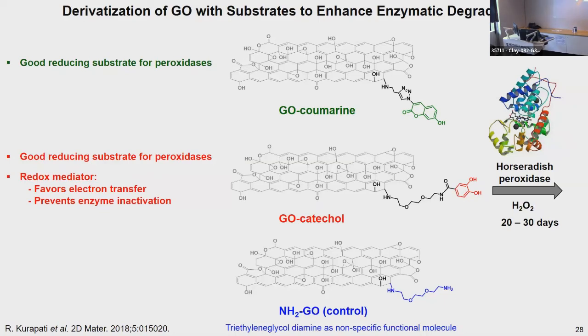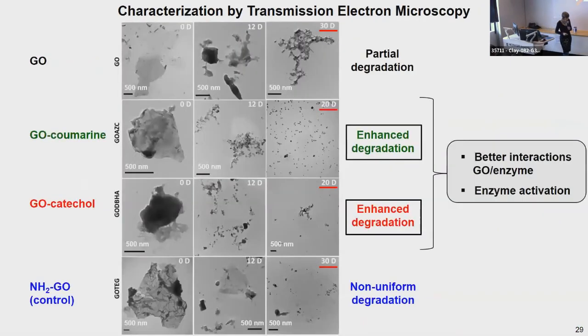So we prepared these two conjugates that we incubated with the enzyme in the presence of hydrogen peroxide to activate the enzyme for a period of 20 to 30 days. We also used this control, an amino graphene oxide with no specific reactivity. So we monitored the degradation by transmission electron microscopy, also by Raman spectroscopy, but today I will show you only the TEM results. So for graphene oxide, this is the graphene oxide before the treatment. And at the end of the treatment, after 30 days, we could see sheets that were partially degraded.